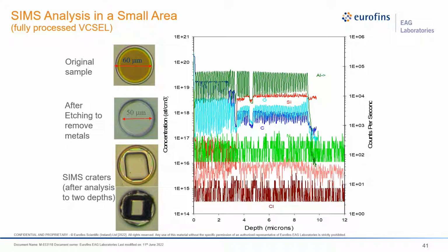The data in the right panel show aluminum plotted in counts per second with respect to the right axis, and profiles for carbon, silicon, oxygen, nitrogen, fluorine, and chlorine plotted in atoms per cubic centimeter with respect to the left y-axis. And you can see how even in these small analytical areas of some 10 or 15 micrometers, we can get very good detection limits indeed.